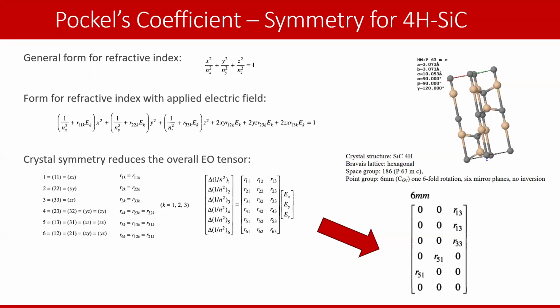And so I took a quick detour by demonstrating and measuring the electro-optic tunability of 4H silicon carbide as a proxy for determining whether or not these devices will work for tuning defects. Because of the crystal structure for 4H silicon carbide, you can drop out a number of the electro-optic tensor coefficients. And so you basically boil something fancy down from the applied electric field in X, Y, and Z here. This is actually the simplified form, because each of these k is actually a summation over 3 of these equations, where k is X, Y, or Z. And so then you drop some crystal symmetry in there, you get a tensor that looks like this. So that's why you go down to 18 instead of 27 tensor elements.